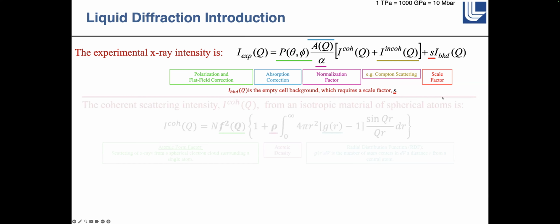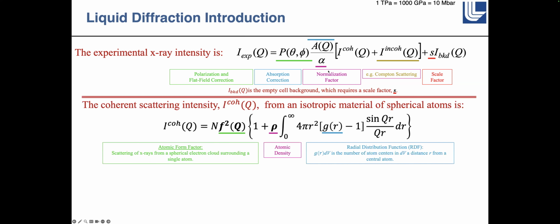So the intensity that you measure in your diffraction is built of a lot of corrections, but it's basically this coherent scattering that we care about. The incoherent is things like Compton scattering, and you've also got background. So all of the underlined things are corrections that you have to apply to the data to start off with. And then once you can pull out the coherent scattering, then you've got the atomic form factor, you've got the density, and you've got basically a Fourier transform here in order to get the coherent scattering. And this G of R is the radial distribution function. And so this is what we would really like to get, kind of the structure of the liquid.